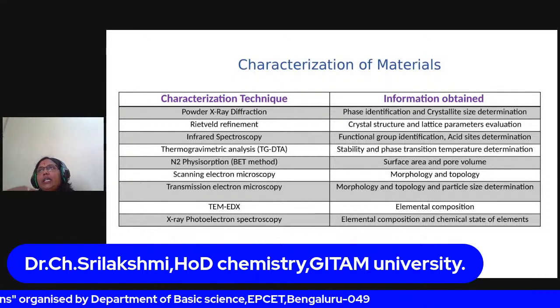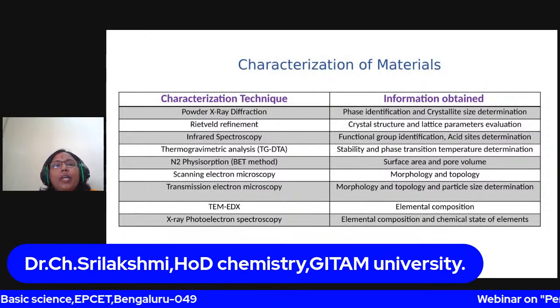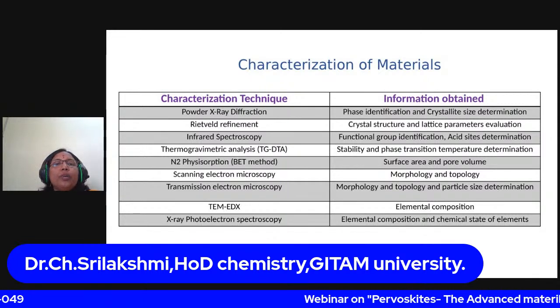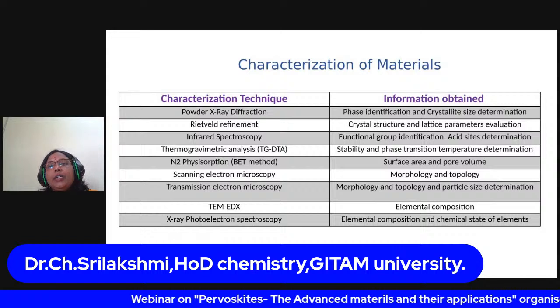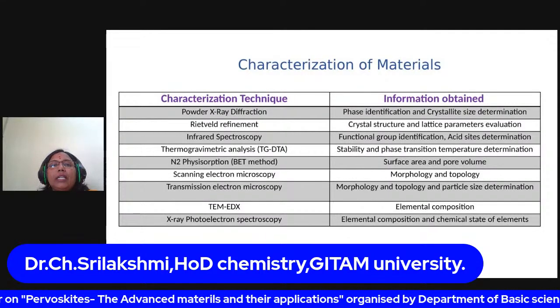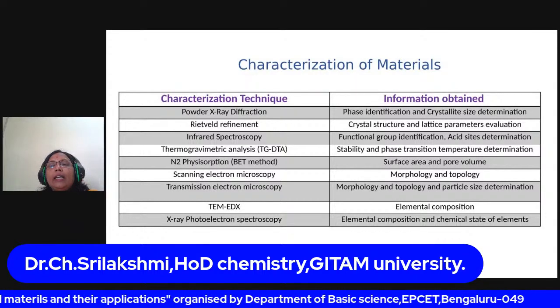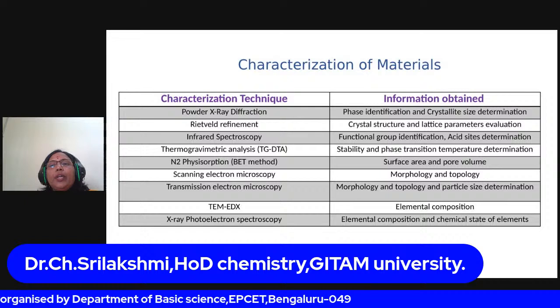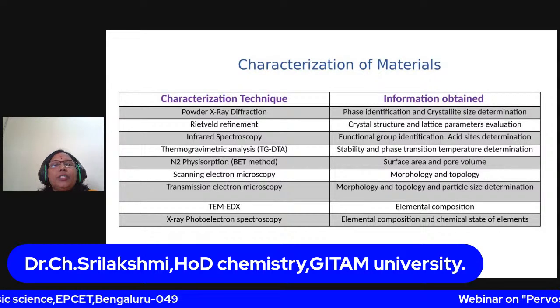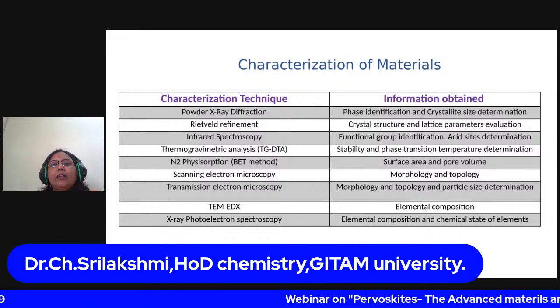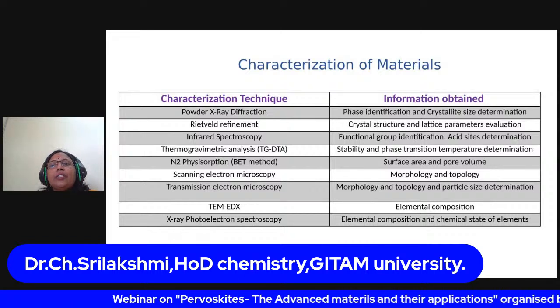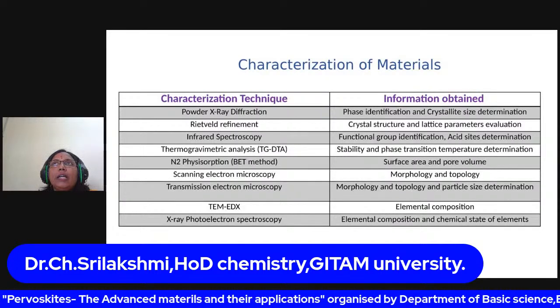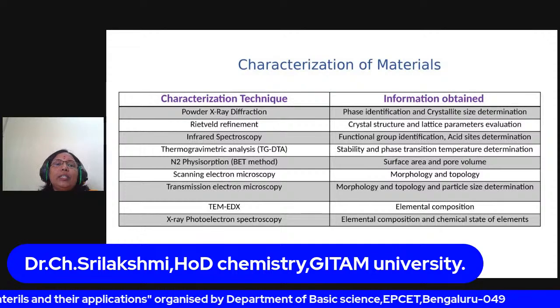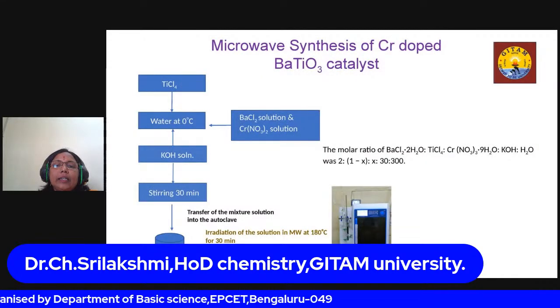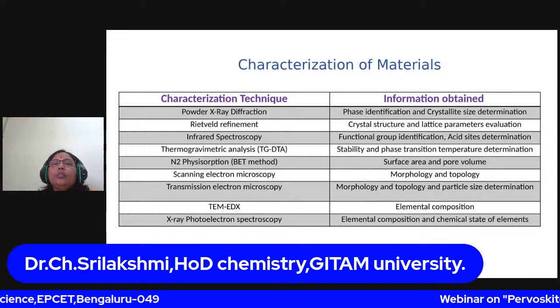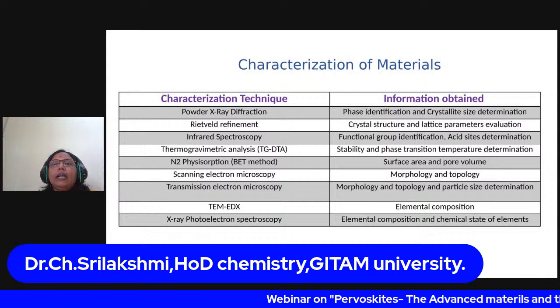Before getting into the details of the work that I have done, I want to give you a brief introduction to the characterization techniques I use for material characterization and the information one can obtain from each technique. With powder X-ray diffraction, you can identify the phase and calculate the crystal size. Rietveld refinement is a theoretical method from which we can evaluate the crystal structure and lattice parameters. Based on that, we can predict the crystal structure of the perovskites. It uses the data generated from X-ray diffraction to give information about the crystal structure and lattice parameters.